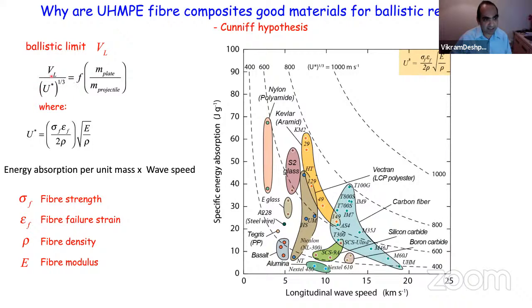So if you increase this u star, you've increased the ballistic limit. Ballistic limit means the velocity at which this projectile will go through the structure. So again, we can go to an Ashby type of plot and plot this energy absorption per unit mass versus longitudinal velocity speed. And these dotted lines are contours of this parameter u star to the power 1/3.